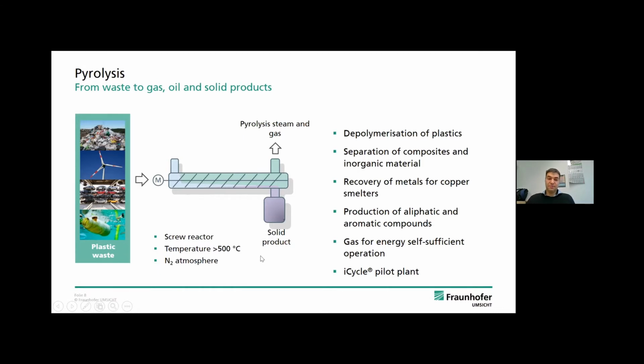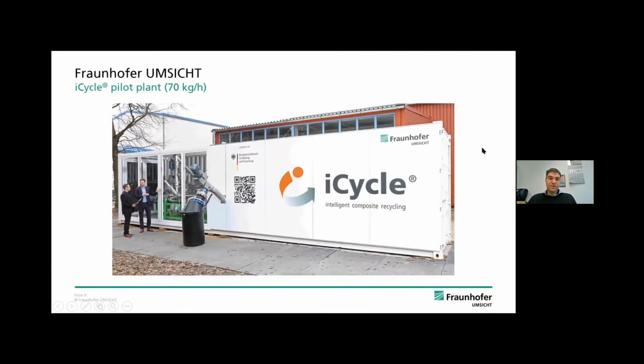Under these conditions, we start with the depolymerization process. So the plastics are depolymerized into smaller chemical units. And we are separating composites and inorganic material from these plastic fractions via a screw system, and we end up with a solid product that is free of organic material. We then also have a pyrolysis steam and gas, and the steam is condensed, giving some aliphatic and aromatic compounds. And the gas, for the moment, is used for energy recovery to have an energy self-sufficient operation, but the gas can also be isolated in future. We have a so-called iCycle pilot plant at our institute, which is capable of converting around 50 to 70 kilograms per hour of plastic waste.